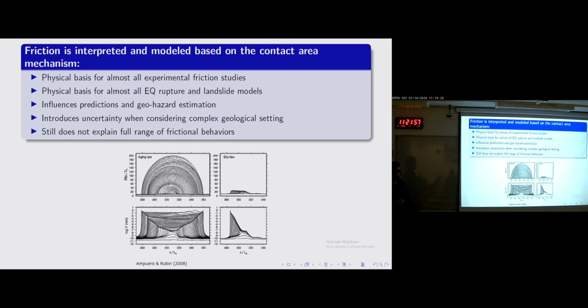And the thing is, up until now, we only use the contact area growth mechanism from a few experiments which are very, very good, but are done at room temperature conditions. So that introduces a lot of uncertainty when we go into more complex geological settings where we have fluids, different mineralogical species, complex chemistries, higher temperatures. So we're using a simplified physical mechanism like contact area growth, which is great, but we're introducing some uncertainties into these models when we go into more complex environments. And I will close this slide and say that even by using this physics-based aging law, or the contact area growth, we still cannot explain the full range of slip behaviors we observe in the lab.